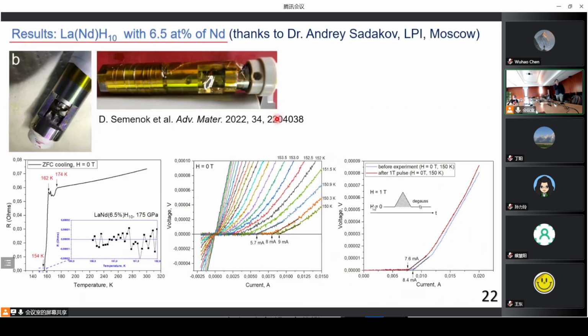Okay, we did this experiment, and it's partly described in this publication, Advanced Materials. We used a pulse magnetic field with diamond anvil cells with the sample. It was lanthanum H10 doped by neodymium 6.5%. The sample demonstrates a superconducting transition, quite narrow, about 8 kelvins. And below 154 kelvins, we can do transport measurements and measurements of critical currents.